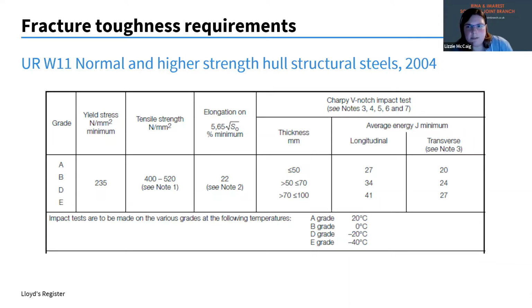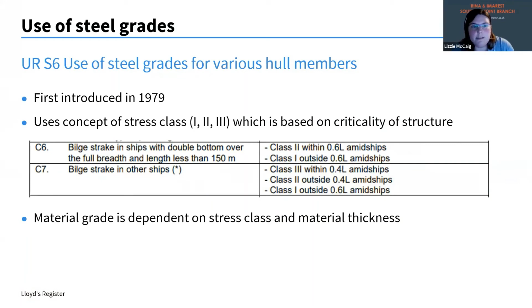But it's not enough to just specify what the material properties should be. We also have to look at how the steel grades are intended to be used. So IACS has another unified requirement, which is UR S6, which was introduced in 1979. And what they do is they divide different structures up into stress classes of 1, 2, and 3, and that's based on the criticality of the structure.